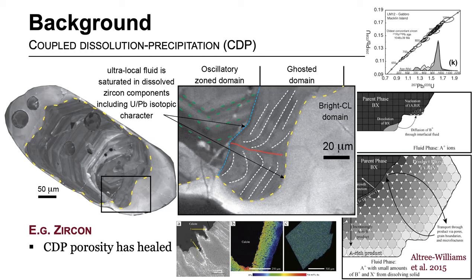Although the grain has been recrystallized, there is a question as to whether the age resets to zero. This depends on the connectivity of the fluid at the interface and the bulk fluid that's driving the process. The cartoons on the right are showing that chemical communication happens through microporosity in the recrystallized domain, in the rim. If the connectivity is high, then there is a good chance that lead can escape, and we might reset the age of our rim domain to zero. If that connectivity is low, then the likelihood of transporting the old uranium lead isotopic character away from the recrystallizing parts of the grain is less likely.